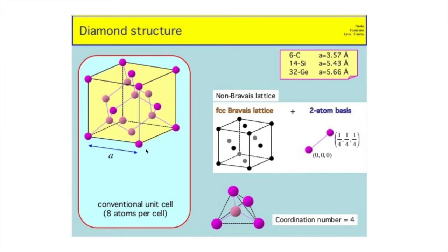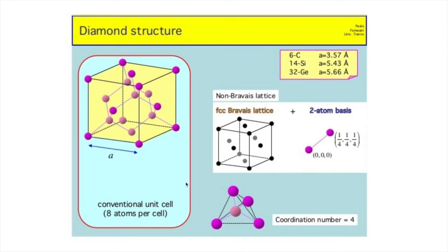So when we talk about the diamond cubic structure, it has an FCC Bravais lattice, because that's the simplest point lattice that we can use to build up that structure. So that's important. And we call this a non-Bravais structure because we have 2 atoms per point. And so that's the other part of this. So we have 8 atoms total per unit cell because we're putting 2 on each point, and FCC already has 4. So that's how we get those numbers associated with the diamond cubic structure.